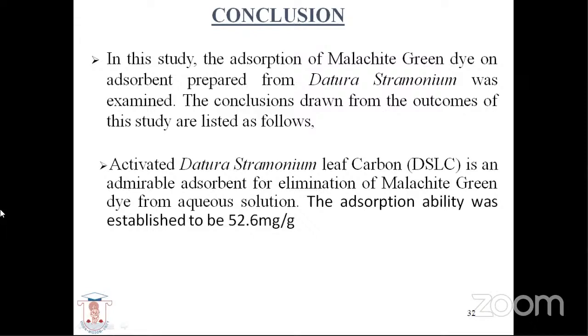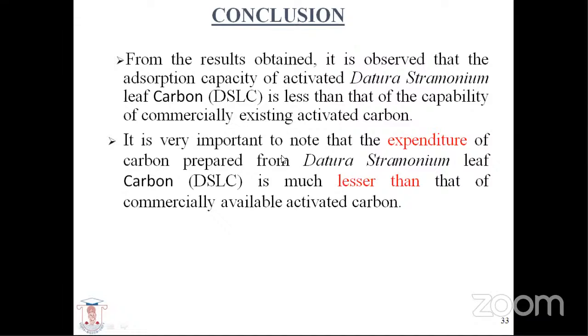The elimination of malachite green can be done like this, 52.6 milligram per gram. When compared to commercially activated carbon, it is 70 to 80 milligram per gram. But when comparing the cost, it is very low compared to the commercially available activated carbon. It is very important to note that the expenditure on carbon prepared from the Datura Stramonium leaf is much lesser than that of commercially available activated carbon. As we are concentrating on low cost adsorbents, we can achieve this, even though the adsorption capacity is lesser than that of commercially activated carbon.